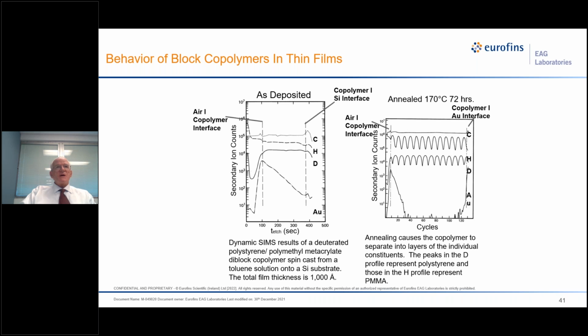I think this is my last example. Many of you ask, well, can you analyze polymers? Yes, we can. Here's a spin coat of deuterated polystyrene and polymethyl methacrylate, diblock copolymer spin cast onto silicon. This is as deposited. And again, it gets to the idea many of you ask, well, can you analyze isotopes? Because the other surface analytical techniques cannot. Well, SIMS, being a mass spectrometry technique, can certainly analyze isotopes. So here we have the hydrogen profile and a deuterium profile.